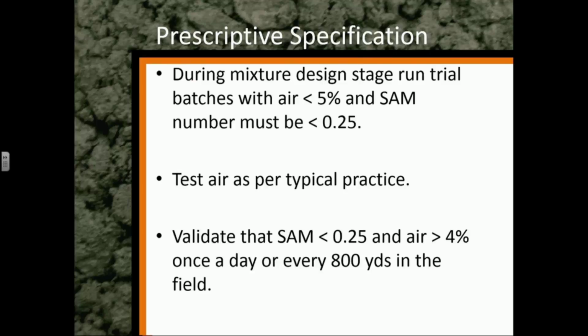I'm going to present 2 procedures right now, and this is evolving and ongoing. One procedure is a very prescriptive specification. And this is a little bit different approach. But during the mixture design stage, you run a trial batch. That's not that different. But you force people to use a low air content. You force them to have an air content to be less than 5%.